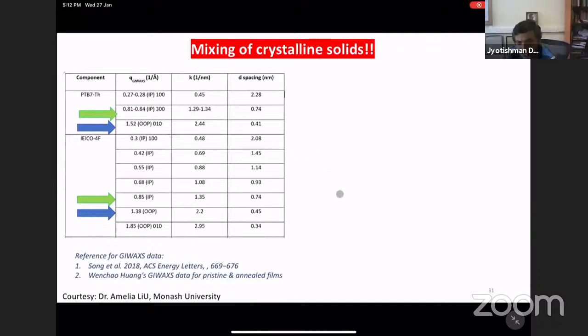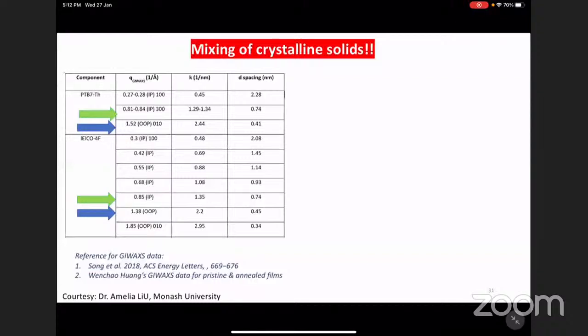So what is the lattice spacing corresponding to? It is corresponding to some sort of crystallinity after mixing. So whether the 2-3 molecule lamellas are being formed in these polymer films, how many chains are staying together, and whether you have mixed one or two of this non-fluorine acceptor into this one, or the non-fluorine acceptor individually, how are they packing, and the polymer chains individually, how are they packing, and on the intermix level, how are they packing. Those all peaks can be seen in the GIWAXS data. These are GIWAXS data, and the earlier one was the cryo-EM data.